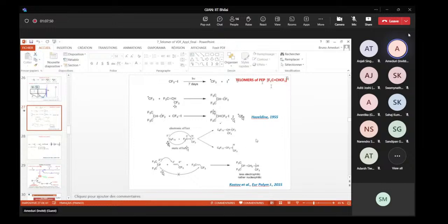Indeed, it was much better to try some copolymerization with PFP, for instance, with trifluoropropene. During the polymerization, we saw that the initiation was more efficient from the perfluorinated radical onto the CH2 of the trifluoropropene rather than onto the CH of the CH-CF3, because of the steric hindrance first, and also because of the nucleophilicity of the CH2 of trifluoropropene.